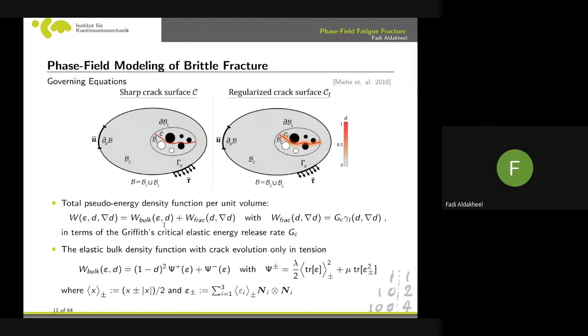Now, what is left for us to describe the energetic criteria is the elastic energy, which can be written in many ways. Here I described it in terms of the Lamé constants, lambda and mu. Focus with me, I have already described it in terms of some degradations. Here is a term, (1 minus d) squared, called the degradation function. We degrade the energy. Why do we do that? Because we have elasticity until some limit. At that limit, the fracture will start, then the stress will drop, so this drop needs to be described with some degradation. So we degrade the energy from when the fracture starts.